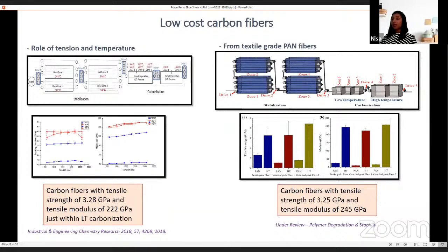In another study, instead of using the normal carbon fiber precursors, we selected textile grade PAN fibers, which is much cheaper than carbon fiber grade. And in the study, we come up with a tensile strength of 3.25 gigapascal and a modulus of 245. So this work is currently being considered for publication in Polymer Degradation and Stability.